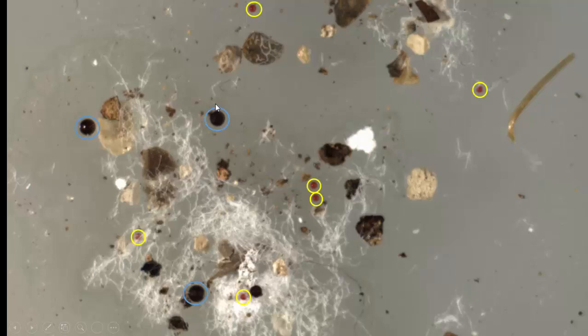And so we spiked with two different types of polymers, and when you visually look at them under a microscope like this, if the particles are broken, then it leads to overestimation, but it tells you that your preparation technique is probably too aggressive. And if you don't recover your particles, you're probably assured that you're losing material throughout your process as well. And so this was very valuable for us.